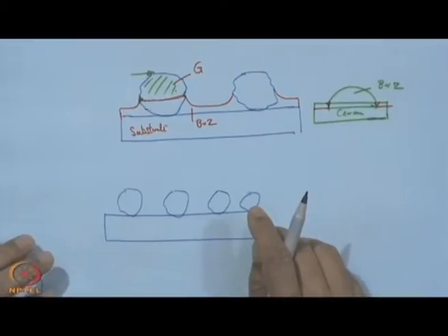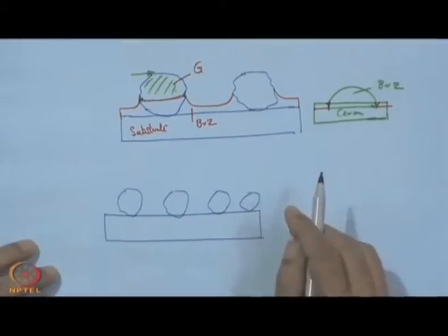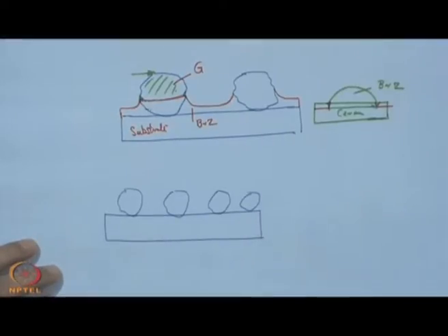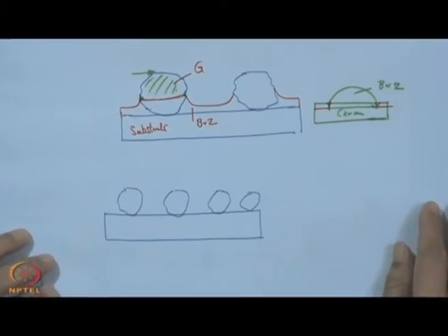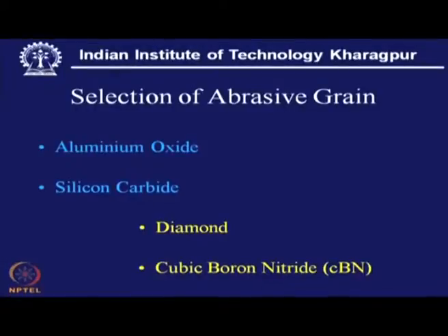So, when it is a molding process or molding practice, what we take normally is a uniformly mixed combination of the bond material and the grit material, that forms a composite mass. So, it is a well dispersed mass or structure, but in this case it is a single layer formation. Now, when it is a composite mass, abrasive wear resistance is not the big issue, because aluminium oxide is known to be inferior to cubic boron nitride, and silicon carbide is also inferior to diamond so far as grinding ratio or wear resistance is concerned.